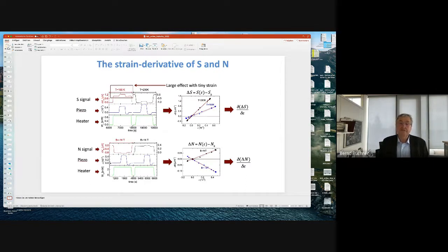You can do the same for a Nernst effect. So this is now the transversal effect. This is typically very small. And here you can even see these changes as a function of a small strain in the Nernst effect. And again, you have to do that in different magnetic fields as well. Then you get the Nernst effect.